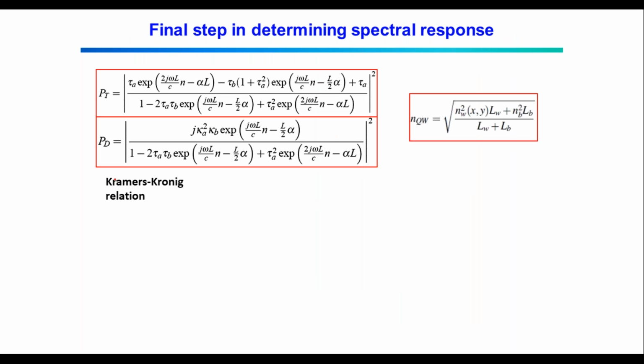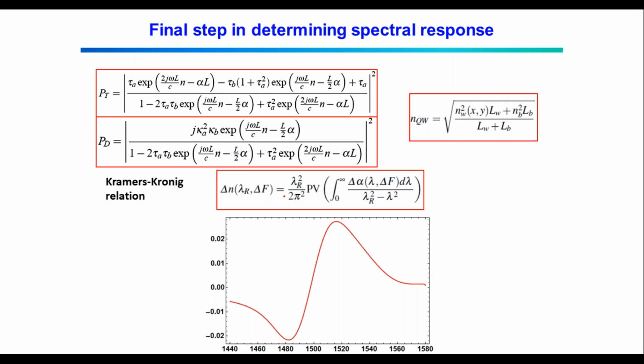So I said that whenever you apply an electric field, let me denote the applied electric field as F. I apply an electric field, there's a change in the absorption of the rings, a change in alpha of the ring, delta alpha. Now, anytime you have a change in the absorption of a material, this is something fundamental to all materials, all semiconductor materials or all dielectric materials, doesn't matter. Whenever you change the absorption of a material, you are supposed to have a simultaneous change in the refractive index as well. So I apply an electric field, I have a change in the absorption, and this leads to a simultaneous change in the refractive index, which I would call delta n.